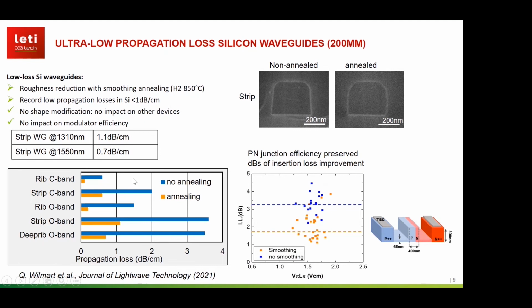It's very interesting when you have a complex circuit, like a transceiver circuit with a lot of elements and long lines, so you can gain several dBs. A question is, is there an impact on other devices? And the answer is almost no. There is no impact on grating couplers, for example. And here I plotted the efficiency of the Mach-Zehnder modulator, VπLπ, and in this direction, the insertion loss of the Mach-Zehnder modulators. You can see that we can reduce the insertion loss by several dBs without changing the efficiency. It means we don't change anything about the PN junction during this process. So it's very interesting for this type of application.